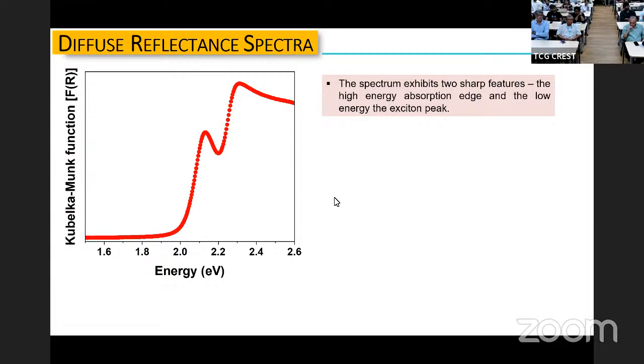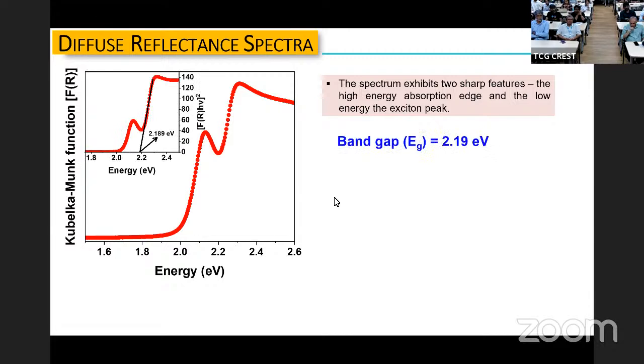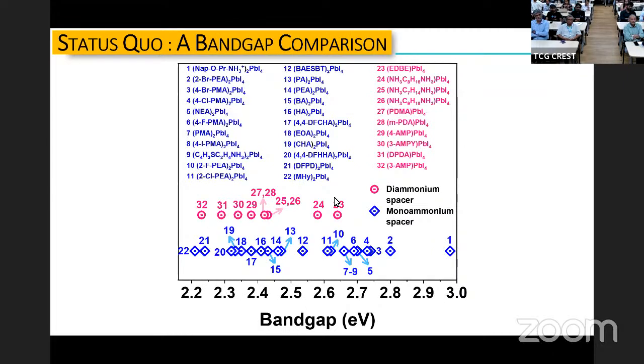So basically, if you extrapolate this edge and find out what its energy is, you can find out what the band gap is. And that is what is done in this plot. It turns out that the band gap of this material is about 2.19 electron volts. How does it compare with the other materials in this class of 2D material with a single layer of inorganic units? That is shown over here.